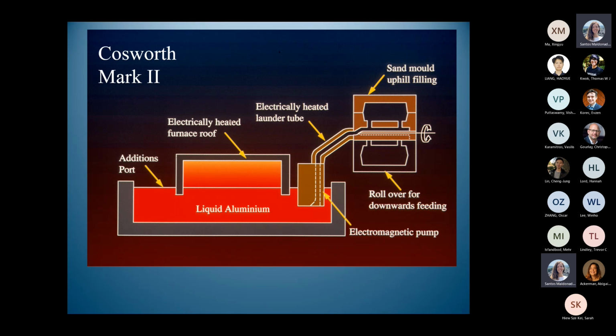So this is what I built. And this made the Cosworth racing engines, and frankly was a godsend to Cosworth. It really got them out of trouble. They finally got engines which finished over the line instead of breaking down halfway round, or worse than that, 50% of the engines failed by fatigue on the test bed. They never got out onto a racing car. So when you're losing 50% of your engines for fatigue, this is a recipe for going broke very quickly. And anyway, when this machine came along, it never once pours metal. The metal only ever goes uphill with the pump into the mold.